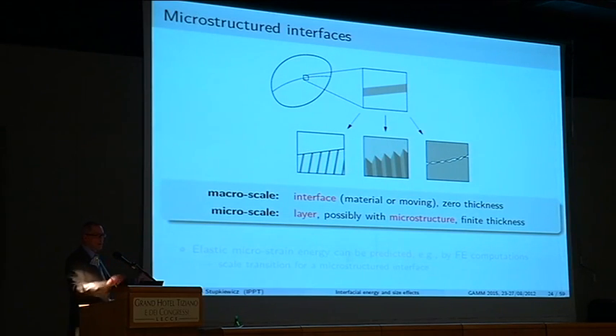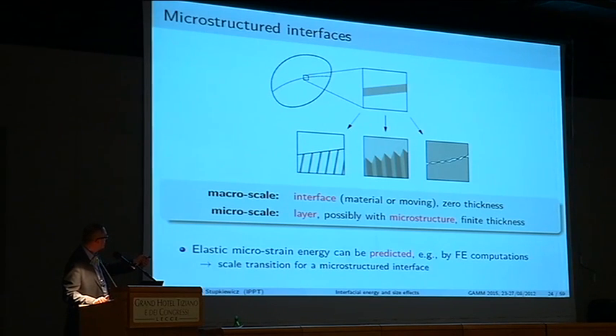So here we apply the micro and macromechanical point of view. So we distinguish between the macro scale and the micro scale. At the macro scale, the interface is a zero thickness surface. It could be a material or moving interface, depending on the system you are considering. However, if you look at the micro scale, this is typically a layer, possibly with a microstructure. And here you have three examples. So we discussed that one, austenite, twinned martensite. This can be grain boundary with martensitic plates terminating on the grain boundary. This is, for instance, in the context of contact mechanics. This is also exactly the same kind of concept of microstructure interfaces.